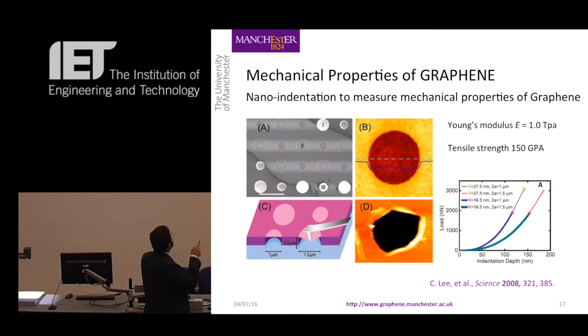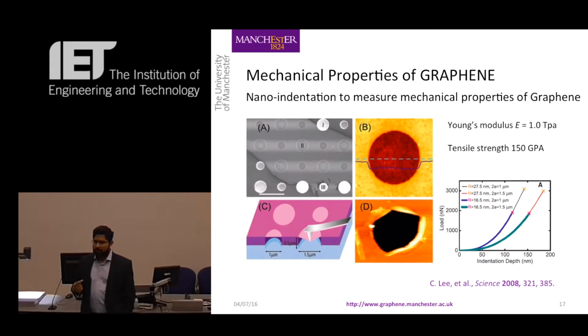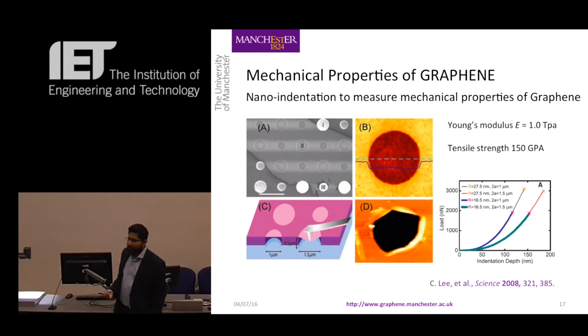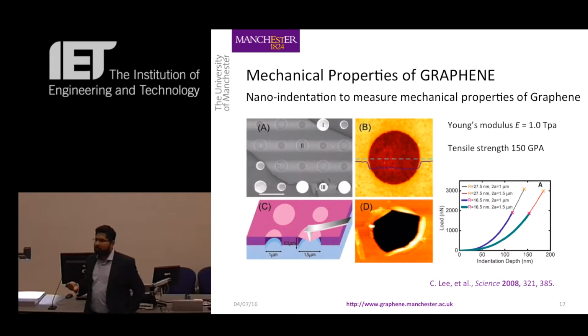What we do is, remember I showed you that image of a hole in a wafer covered in graphene. So we make something like that. We take an extremely sharp needle and we try to puncture the hole. It's like bursting a balloon, except that the needle that we use has to be made of diamond, otherwise the needle will break. So we puncture the graphene, and then we measure the force that it takes to puncture the graphene, and then we use a fairly complex mathematical model of that interaction to indirectly extract the strength of graphene.